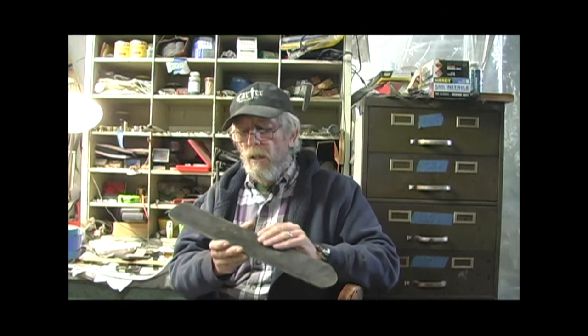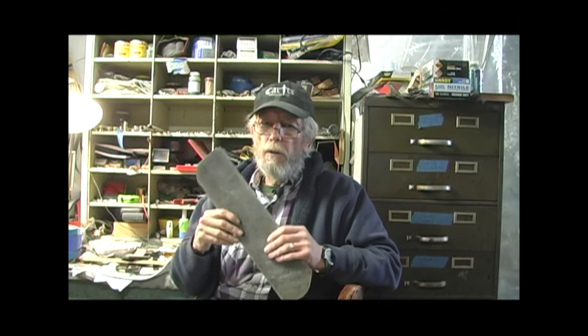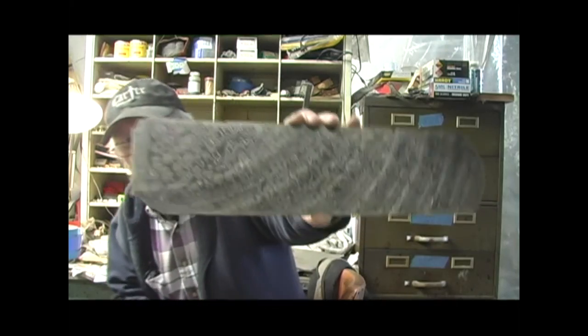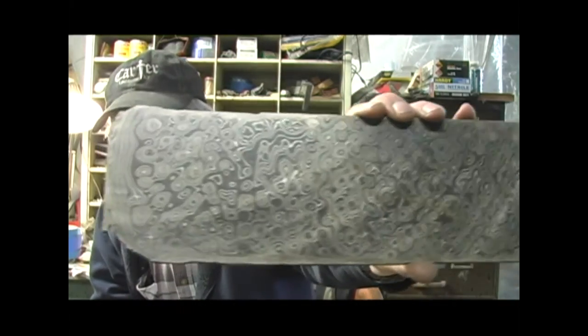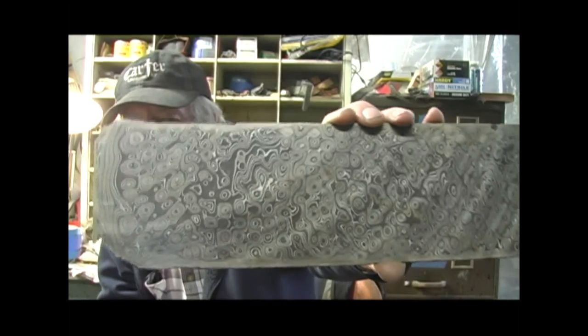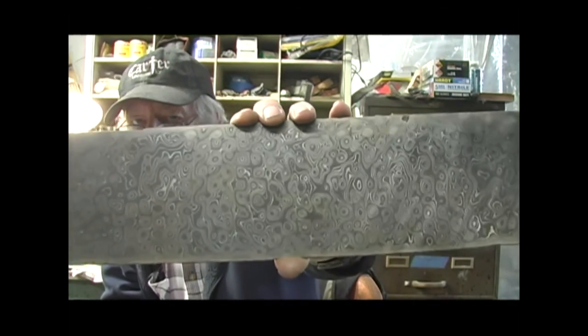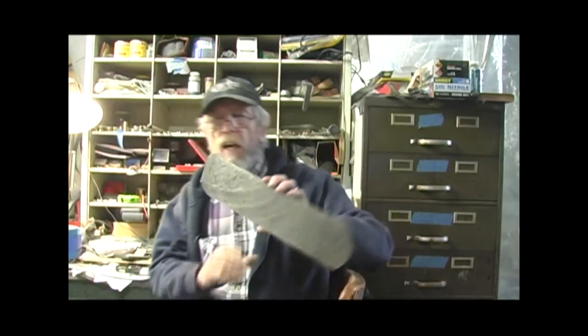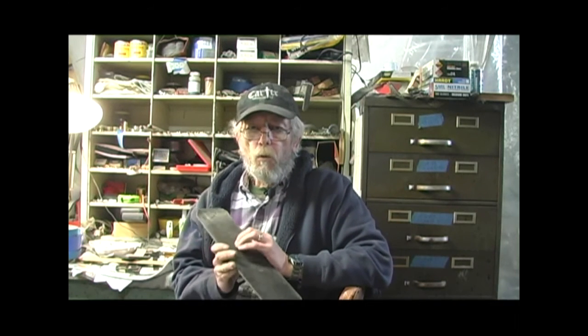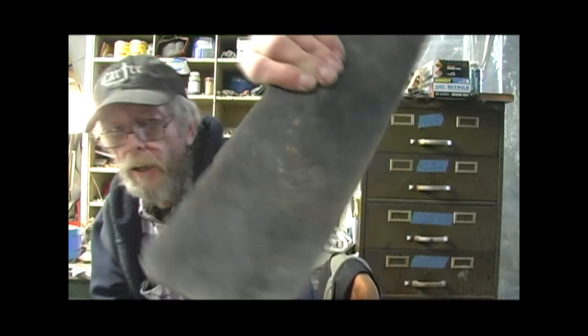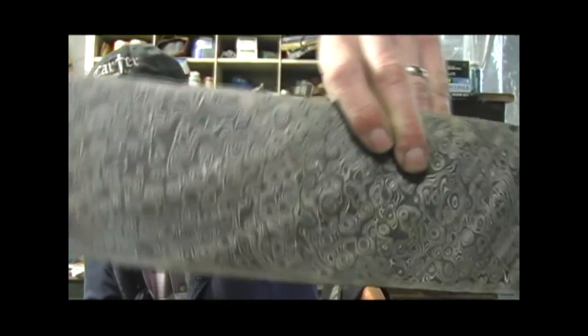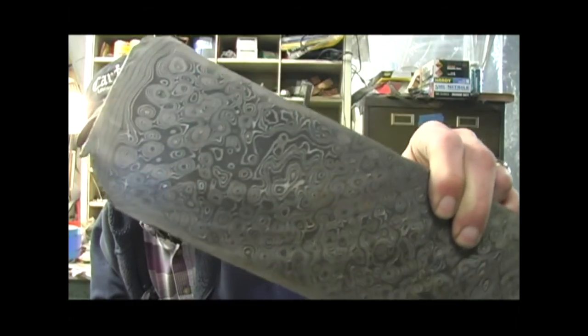And there's different ways you can fold this. There's different dies you can use to hammer it out that give you different patterns. And that pattern actually shows up when the steel is etched in an acid bath. The acid will react differently with the different types of metal that are in here. The nickel won't etch at all, it won't darken. And that's what gives you the bright silvery lines, is actually the nickel that did not darken. It gives you contrast.